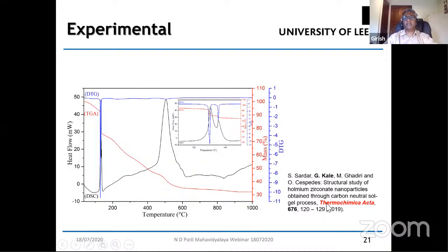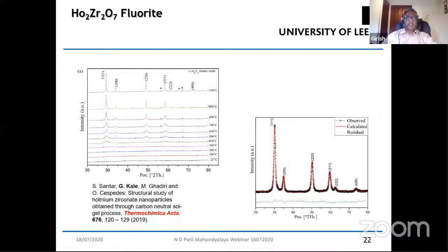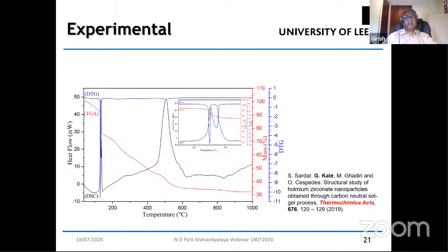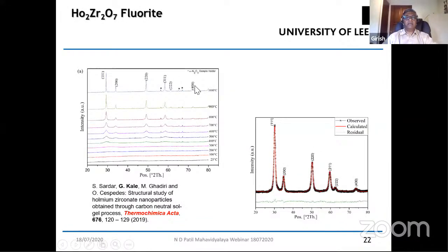And this particular work was published recently by us in Thermochimica Acta, which is part of one of my PhD students' work. We also did high temperature X-ray diffraction to support this, because DSC TGA is a dynamic technique. So instead of just looking at the X-ray diffraction pattern at the end point of calcination, we did some temperature programmed study of the X-ray diffraction pattern from room temperature up to about 1000 degrees Celsius. And we recorded the X-ray diffraction pattern in situ in a controlled environment.